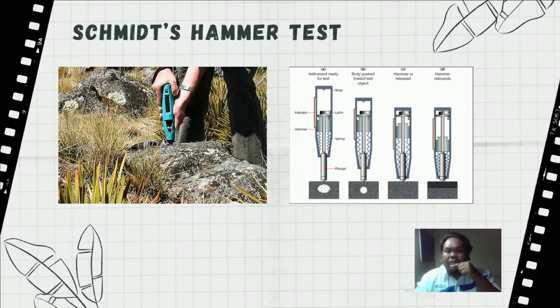during the test, which should be flat and smooth. The rebound reading will be modified by the hammer orientation, where gravity will increase the mass rebound distance when applied upward, for example on the underside of a hung slab, and vice versa for tests conducted on a floor set. The Schmidt hammer measurements are made on a relative scale spanning from 10 to 100.